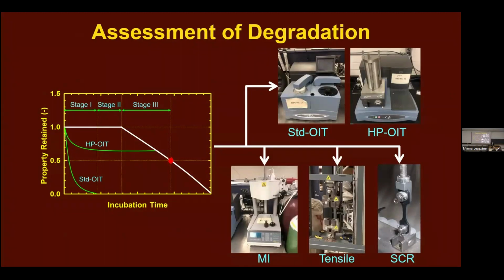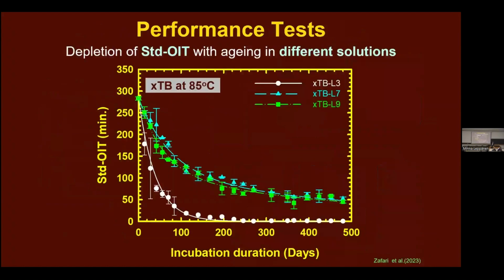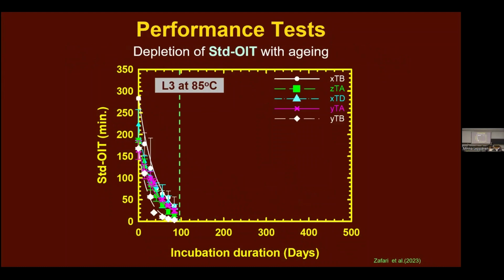So we test for the OIT, and here's some data for one particular geomembrane in 3 different solutions. And you see the depletion of the antioxidants on the left-hand axis versus incubation duration. And you can see the solution makes a huge difference. The L7 is at a neutral pH. The L9 is pH 9. L3 is not at pH 3. It happens to be a reference leachate. But you can see that the solutions give very different response.